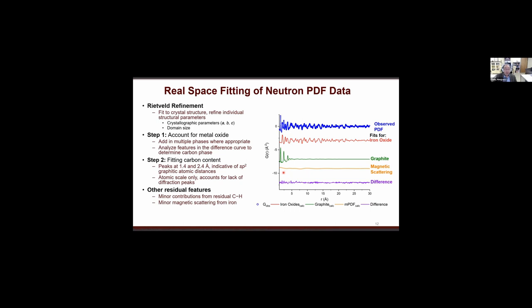Atomic scales only accounts for the lack of diffraction peaks for the graphitic kind of structure there. And then there are other residual features as well, such as the minor contribution from residual CH bonds. We didn't put it here, but it's very minor. And then the minor magnetic scattering from iron, which is the orange curve there. And when you add everything together, you can actually get this difference map.